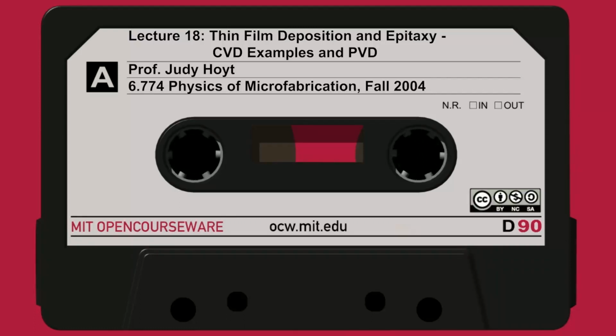In fact, LTO is a very common acronym you'll find in the fab. LTO is, as we call it, low temperature oxide. Typically, LTO is put down between 350 and 450. That's really a more reasonable range. In order to get reasonable properties, to reduce the etch rate and things, people usually have to high temperature anneal LTO. So they have to, what they call, densify it because it's non-stoichiometric SiO2. In modern fabs, you will also find a very common process called TEOS.